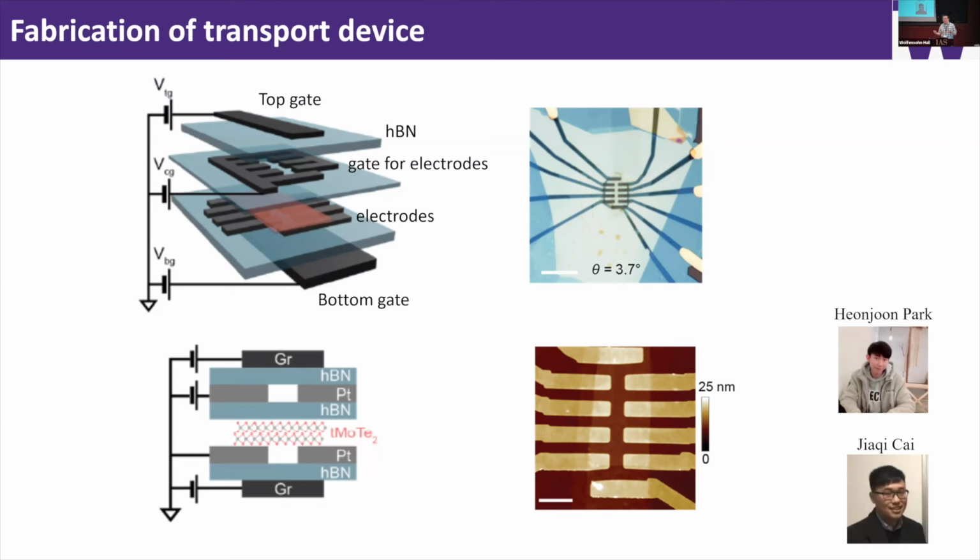Initially what we had was on the order of 100 to 200 kilo ohm. And now we can achieve each electrode contact on the order of 20 to 40 kilo ohms. On the bottom is just the side image. We have these graphite gates, we have a local Pt contact, and then on top, we have these local gates for each contact. Now the right-hand side is an optical image of a device with a 3.7 degree twist angle, and the bottom is the atomic force microscopy image.